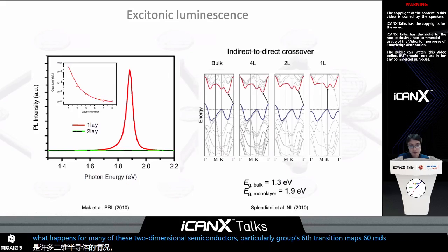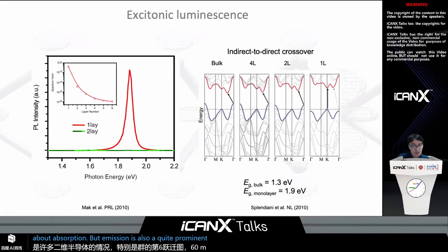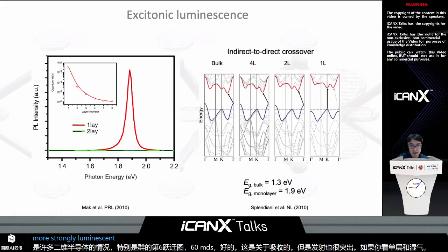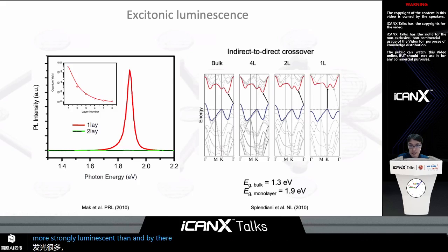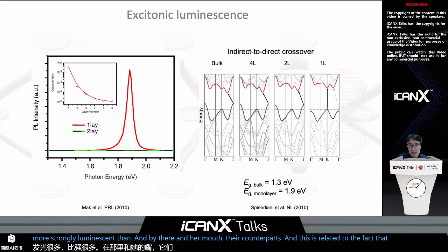Okay, so that was about absorption, but emission is also quite prominent. If you look at single layer MoS2, it's much more strongly luminescent than its bilayer and multilayer counterparts. And this is related to the fact that single layer happens to be a direct bandgap semiconductor, whereas its multilayer counterparts are indirect gap semiconductors.